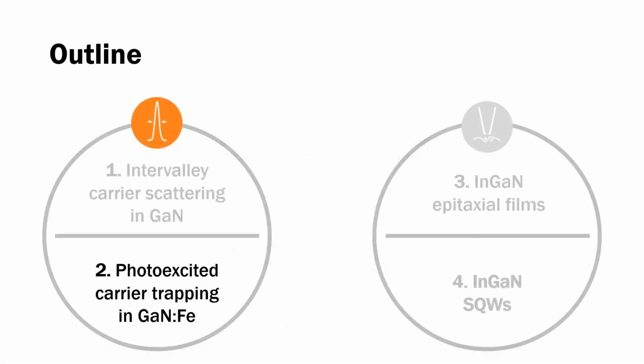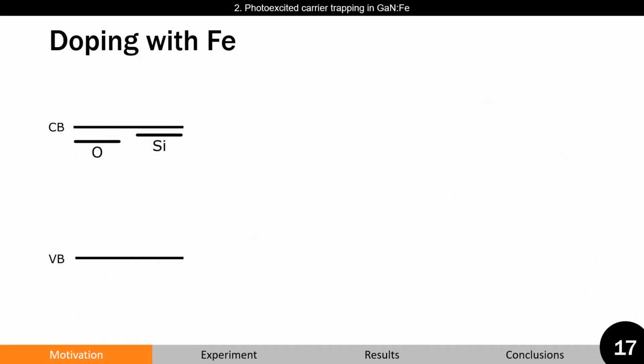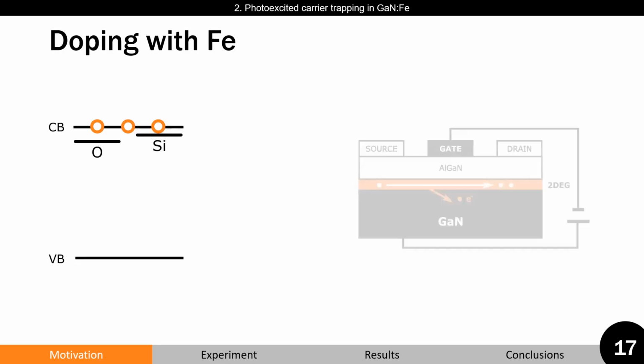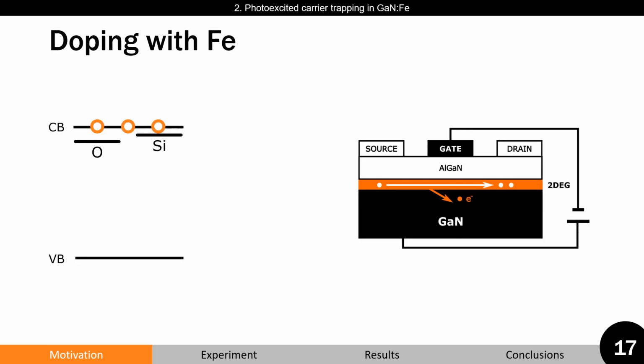In research project number 2, photoexcited carrier trapping in iron-doped gallium nitride was investigated. Gallium nitride is often contaminated with silicon and oxygen, which act as shallow donors and result in high peak carrier concentrations at room temperature. Building devices directly on unintentionally doped gallium nitride, for instance, a high electron mobility transistor, would result in leakage currents, which reduce performance and lead to premature device degradation.